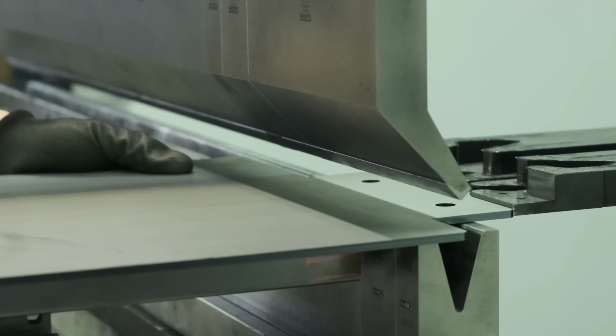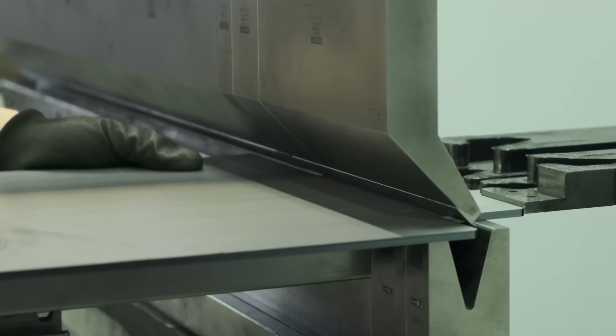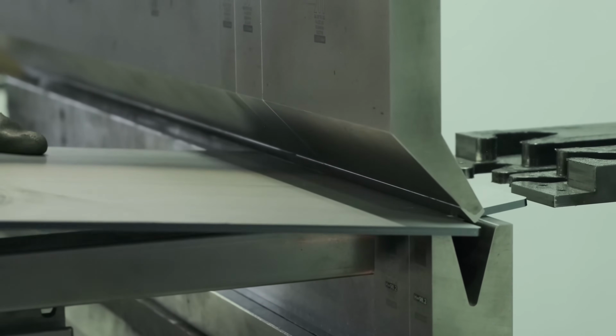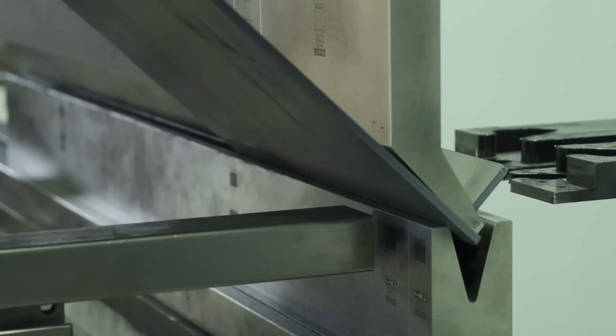But why does an AISI 304 sometimes attract a magnet only on the bent edges or deformed areas? The answer lies in martensite, which is induced by deformation when 304 undergoes cold working, such as bending, drawing, or stamping. Part of the austenite can transform into martensite, which is ferromagnetic. The practical result is a 304 that remains barely magnetic in the areas that weren't worked and shows noticeable attraction where it was deformed. This doesn't mean that the material is fake or of low quality. It's a well-known metallurgical effect in austenitic steels, with certain combinations of chromium and nickel.